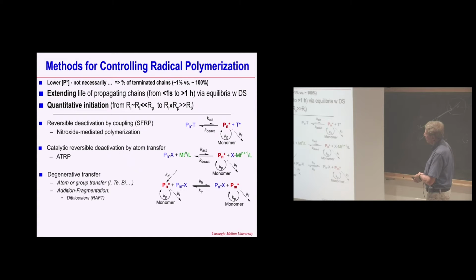So why not use, for example, bromine or chlorine? Unfortunately, this bond is too strong, and you would need to work at maybe 300 degrees to break this bond with a sufficient frequency. So many side reactions, energy extensive, nobody would do that. So can we use a catalyst which would lower activation energy from, say, 60 kilocalories per mole to maybe 10 or maybe 5, and you can work at room temperature in an efficient way?